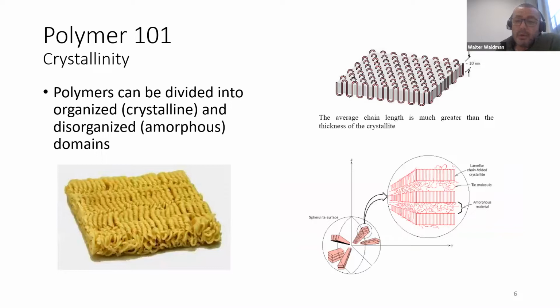And also, one important thing to understand polymer degradation, microplastics, and what's going to happen with art as a function of time is the crystallization. People usually don't know that polymers can crystallize. If you have crystals, you always have brittleness. As a function of time, we can delay that, but we cannot avoid that. If the polymer is crystallizable, it's going to crystallize. Somehow, eventually, it's going to crystallize. When they crystallize, they become brittle. They can produce microplastics.